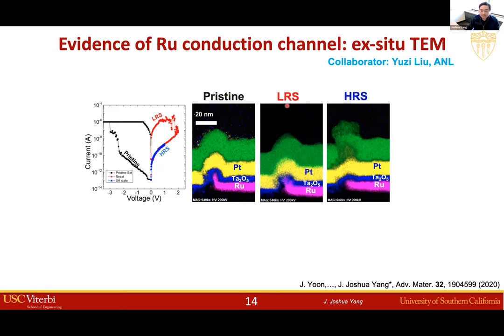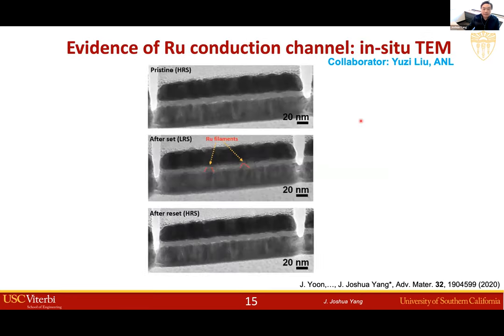And for the device that was switched to low resistance state before the TEM sample preparation, you can see ruthenium actually penetrates through the oxide, reaching the top electrode. And for the device that was switched back to high resistance state before the TEM preparation, you can see ruthenium is cleaned up from the oxide layer. And so this is ex situ TEM. We also did the in situ TEM. I think you did this.